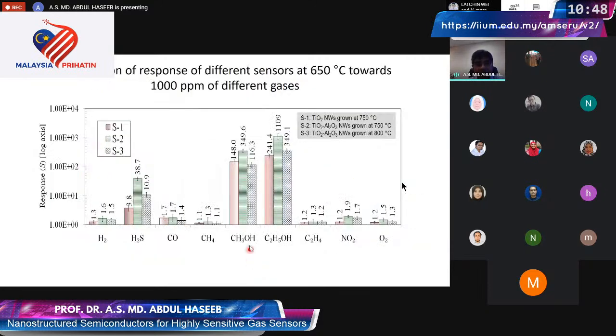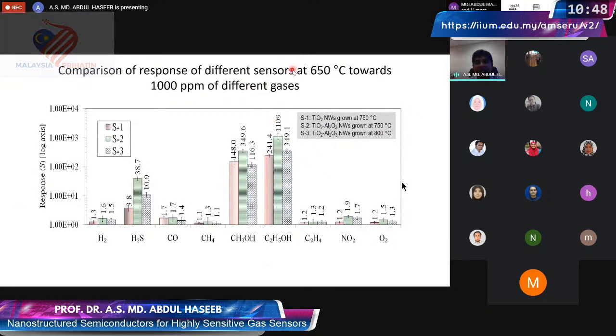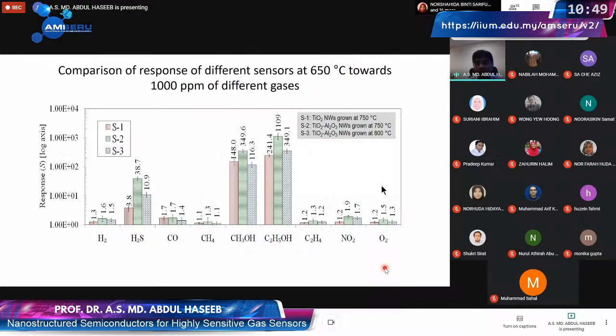So to summarize what we see, if you plot the response, we see that the gas sensor that we have designed has sensitivity towards methyl alcohol, ethyl alcohol, and hydrogen sulfide. And for the rest, the response is quite low, which means that this particular sensor can be targeted for measuring these gases in the presence of other gases, because those other gases will not interfere appreciably with the measurement.